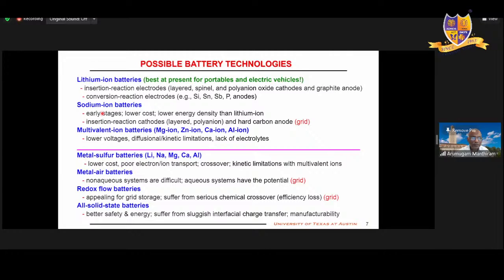So anytime we dope, we always get better cyclability, better safety, and better air storage stability. And why is it? This is good for physics people. You might have heard about, or you may be teaching your students, Anderson localization. In this layered octahedra, the metal ions see each other directly. The electron is very well delocalized. As soon as I put in aluminum or magnesium, they are inert. That electron delocalization is perturbed, so the band will narrow. It will introduce Anderson localization, an impurity band.